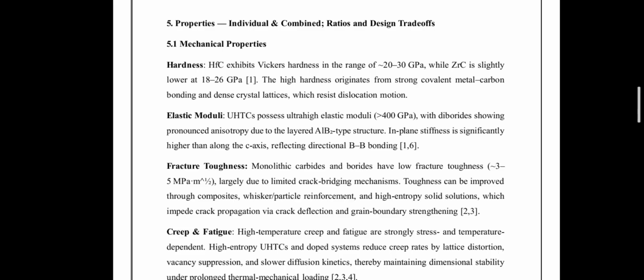This hardness originates from the directional covalent bonding, which strongly resists dislocation motion. Elastic moduli typically exceed 400 GPa. In diborides, the AlB2 type layered structure leads to pronounced elastic anisotropy. Stiffness is significantly higher in the basal plane than along the c axis, reflecting strong in plane B-B bonding.